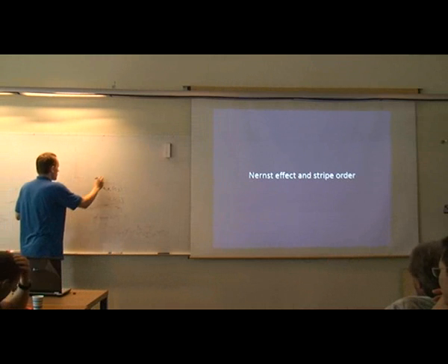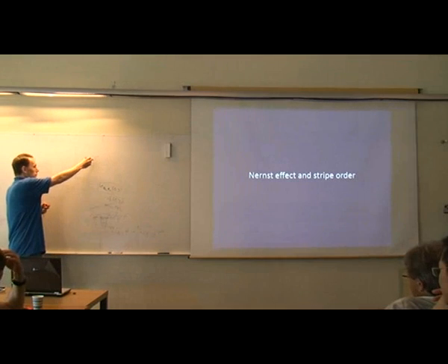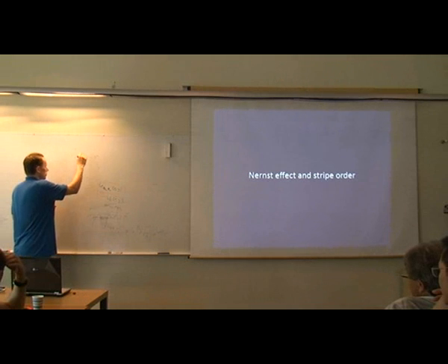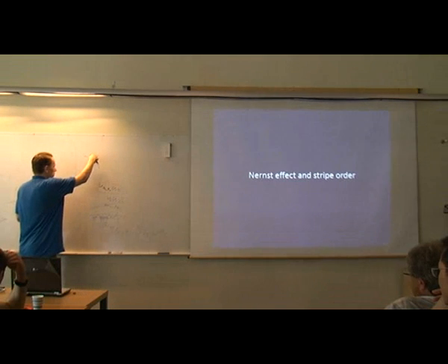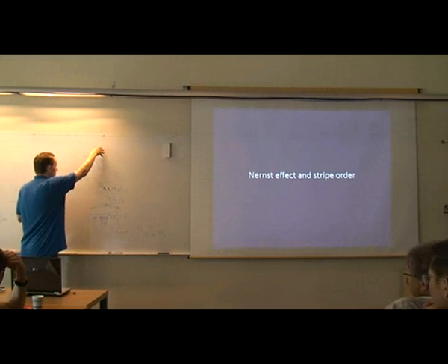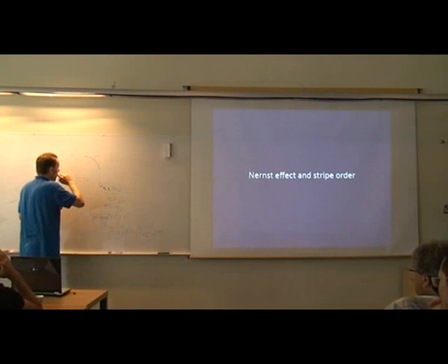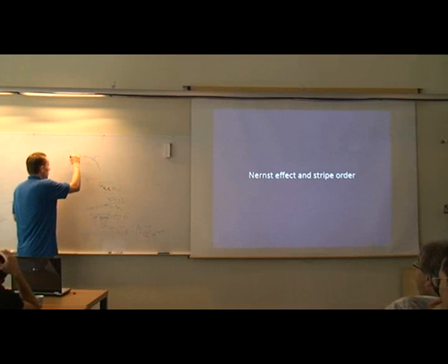It's quite different. You see a pseudogap phase boundary at some T star, where you see some linear temperature dependency, say, at this doping. Across this line you usually define a change from linear resistivity in temperature to quadratic or something else. And the Nernst signal usually has an onset that is much lower in temperature, which is then called T nu.